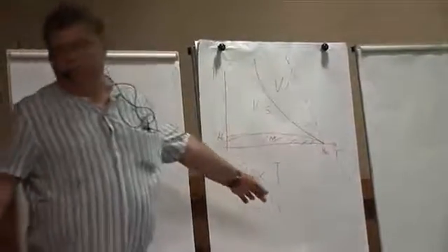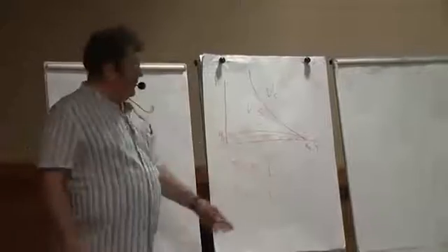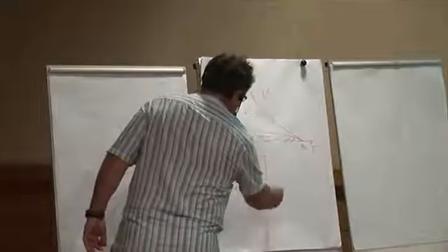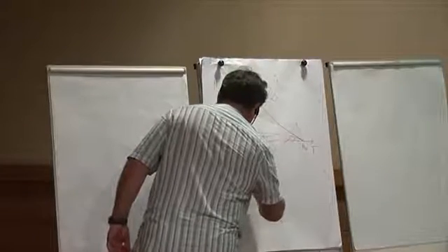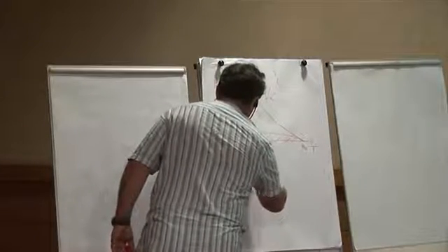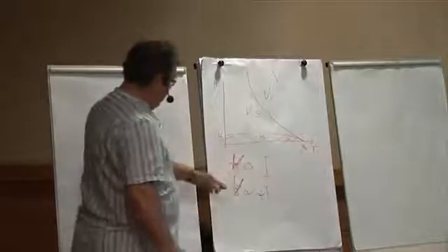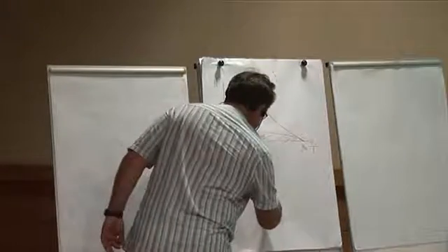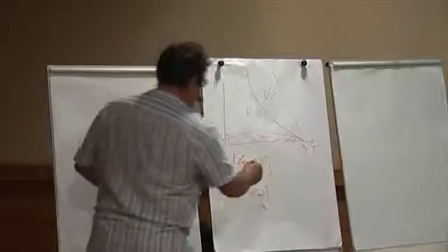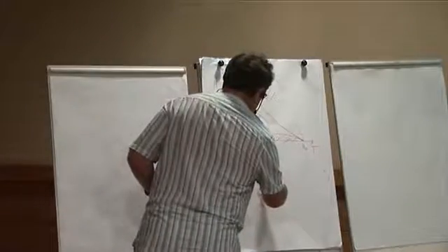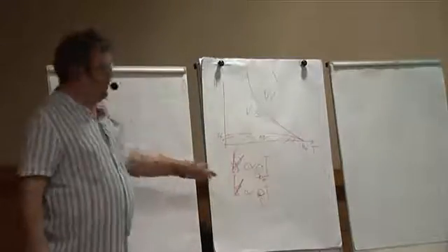Only the constant in front of the current is different. So here will be the coefficient for the normal state. Voltage or dissipation is proportional to the current. Here will be the normal state resistivity. And here will be what is called flux flow resistivity, which is smaller than this one.